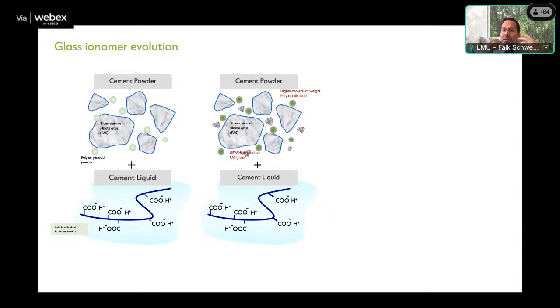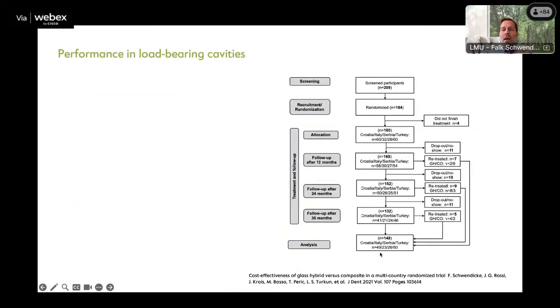And this has evolved over the last decade quite a lot into something which we now oftentimes also call glass hybrids, which the term is not without any problems, so I wouldn't overstate it. We can use the term glass ionomers nevertheless. But the difference with this new evolutionary step is that we have longer chains in the acids, and we have a second phase of a smaller particle in the glass phase. And that smaller particle with a higher surface to volume ratio leads to better cross reaction and hence better surface and fracture resistance. That said, for me, the most important thing is clinical data.